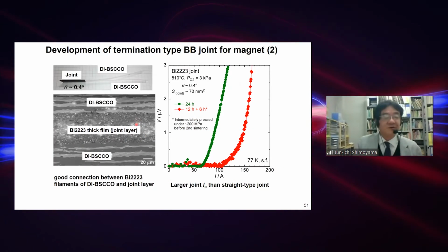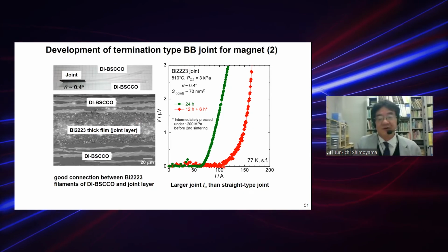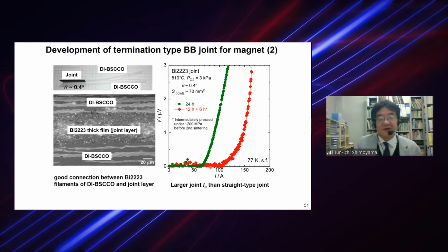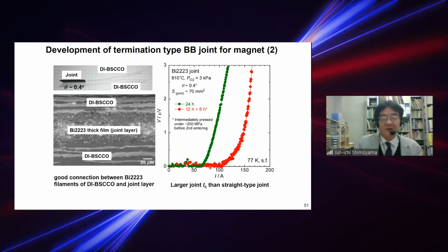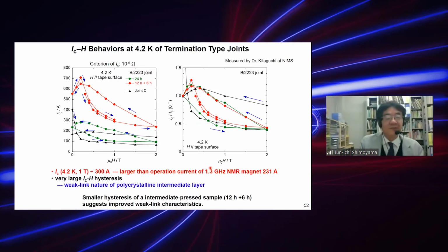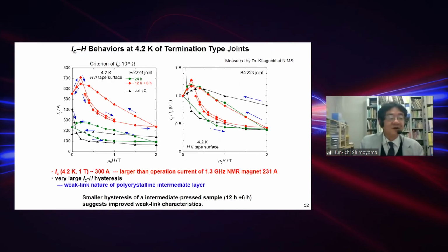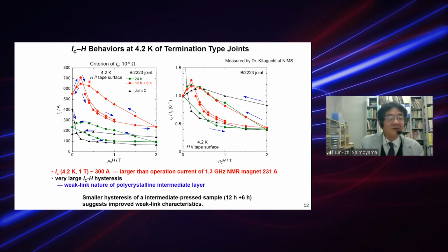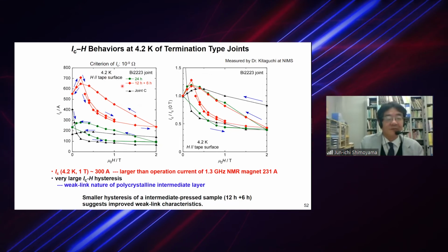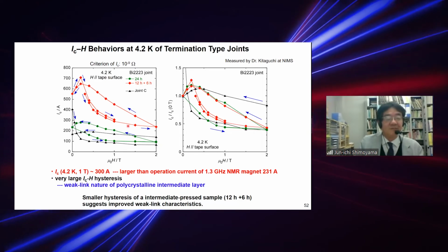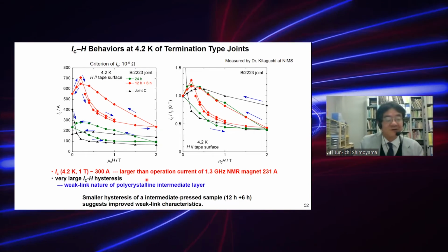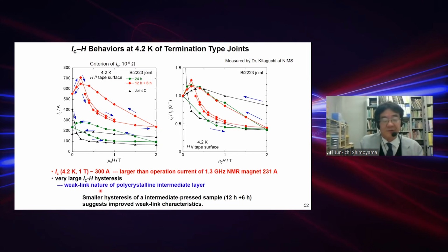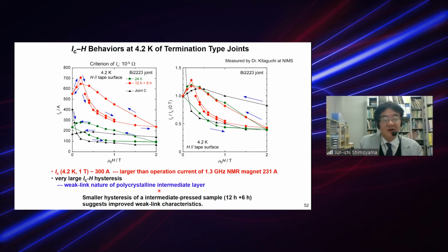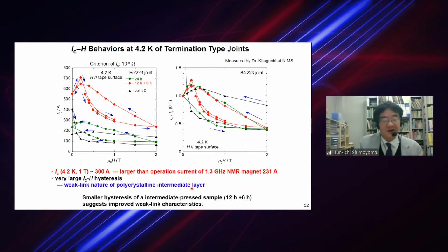Also for this joint configuration, we can develop a 300 amps class joint between Bi-2223 tapes, and this joint can carry very high current at 4 Kelvin while showing big hysteresis. This means the weak nature of the polycrystalline layer still remains at the intermediate layers.